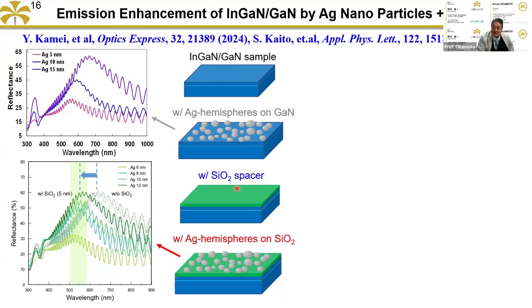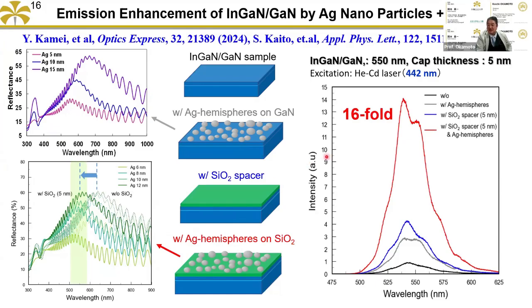Then we put a silicon dioxide spacer sheet between the metal nanoparticle and the gallium nitride. If so, we can avoid the destruction of the metal nanoparticle, and also the refractive index of the silicon dioxide is very low, 1.5. That's why we can blue shift the resonance peak. Then using this structure, finally, we can obtain more than 10 times the enhancement, even for the green light. So if we can apply this to the device structure, we can overcome the green gap problem.